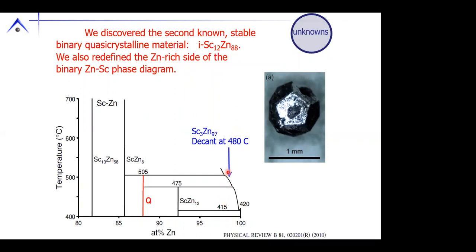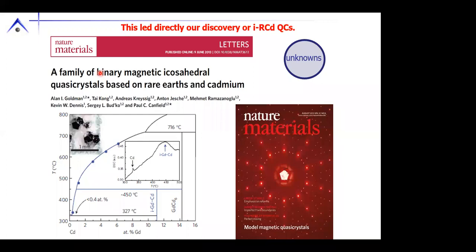I really thought this was not my job, but we had to refine it and correct it for this other peritectic compound. And what we speculated was this quasicrystalline phase is a low peritectic compound adjacent to ScZn12, which is what's known as a crystalline approximant. It has a crystalline unit cell, but it has motifs that are often recognized as being associated with quasicrystalline ordering. Okay. Now, this discovery led directly to the discovery of the rare earth cadmium icosahedral series, because GdCd6 is also a crystalline approximant.